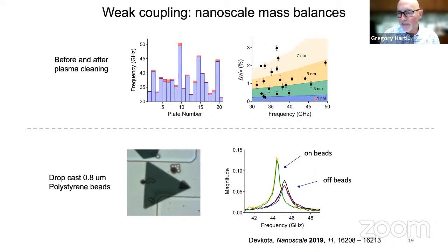And the different lines here are calculations for what would happen if we remove different thicknesses of organic material from the surface. So our experimental results are consistent with removing about 3 to 5 nanometers of organic material, and that's about the thickness of a bilayer of CTAB, which is what these things were coated in. So that seems to make sense. Okay, this is a bit more interesting mass loading experiment.